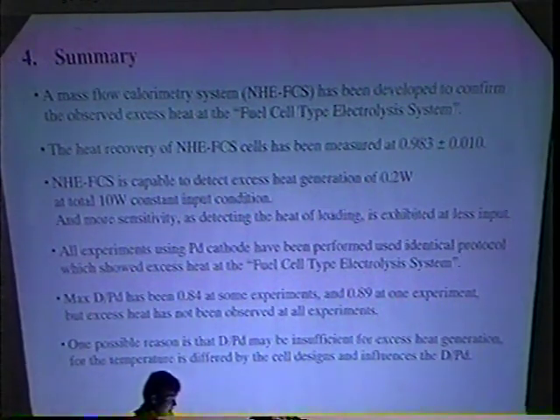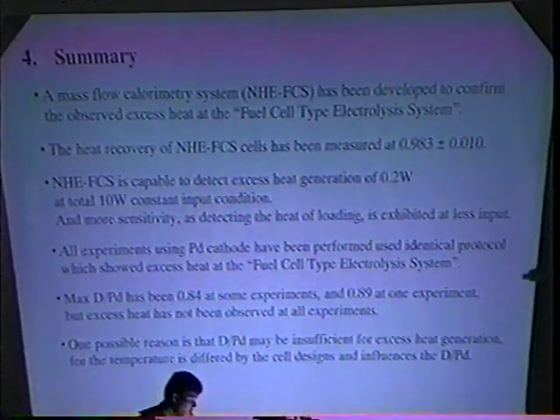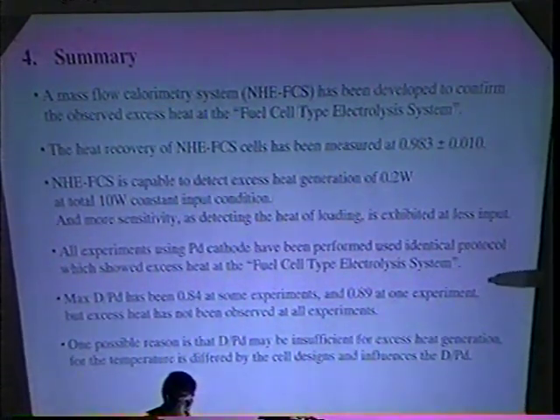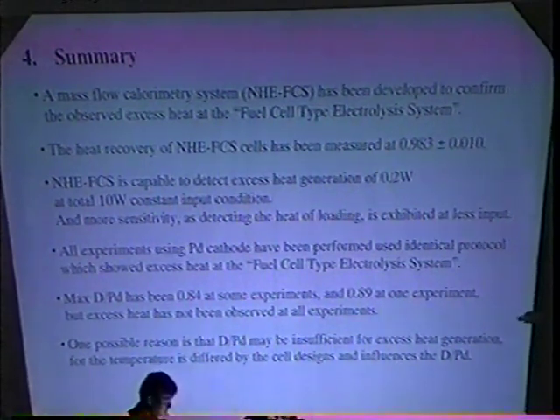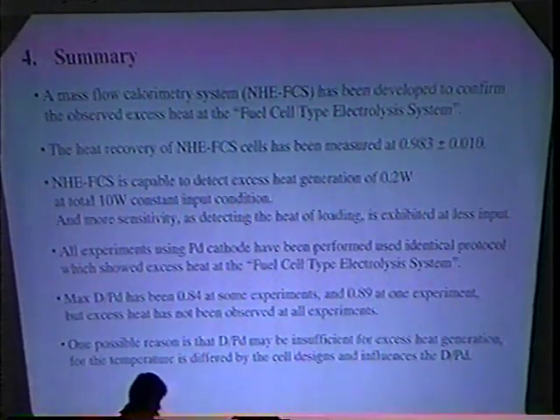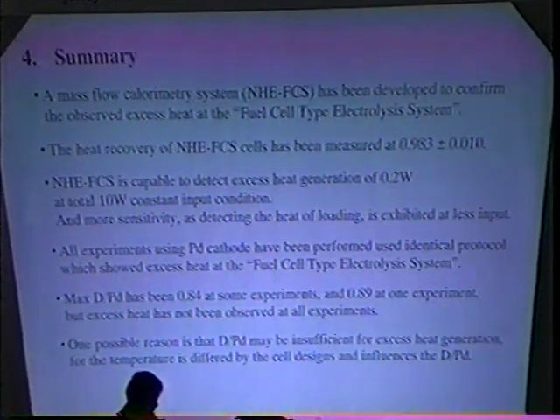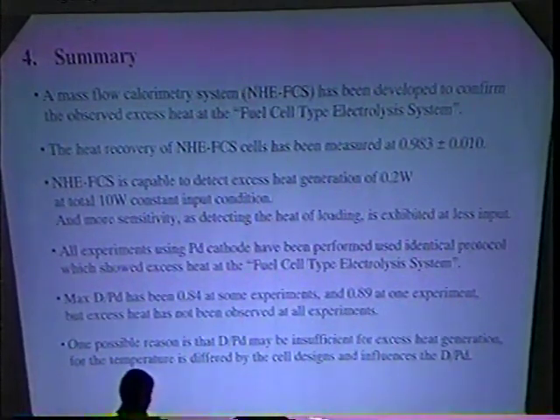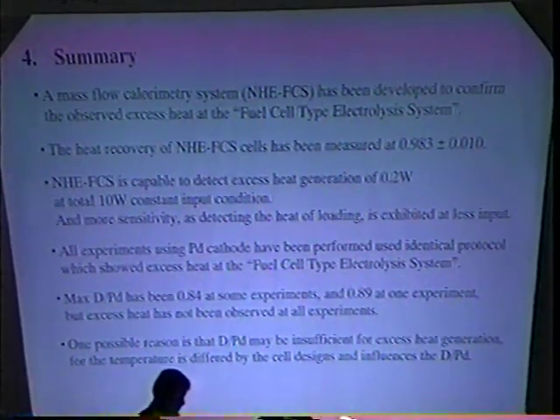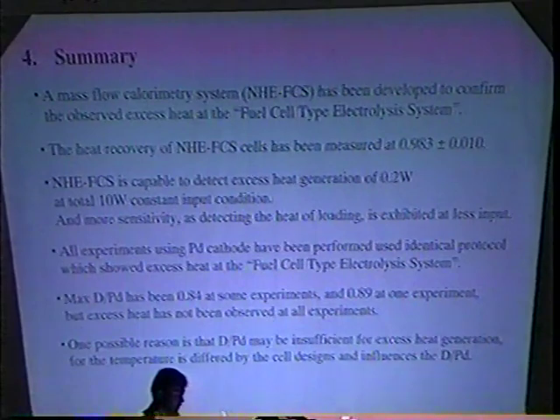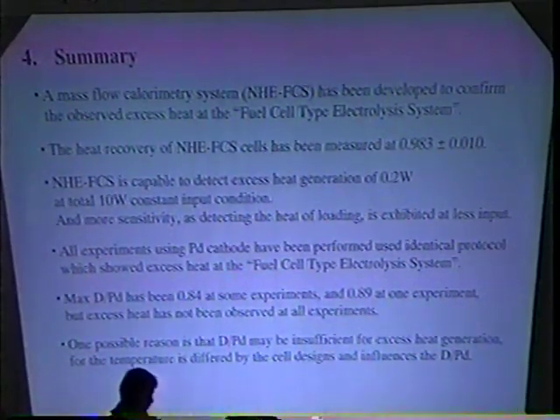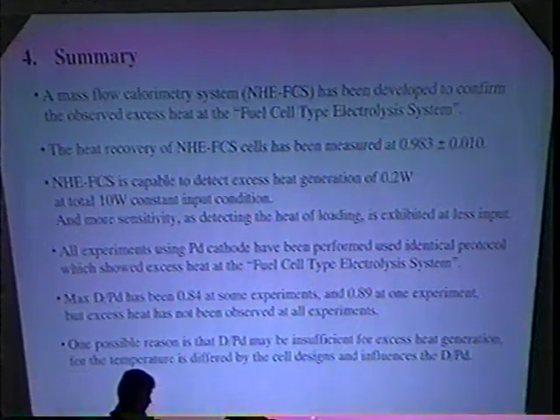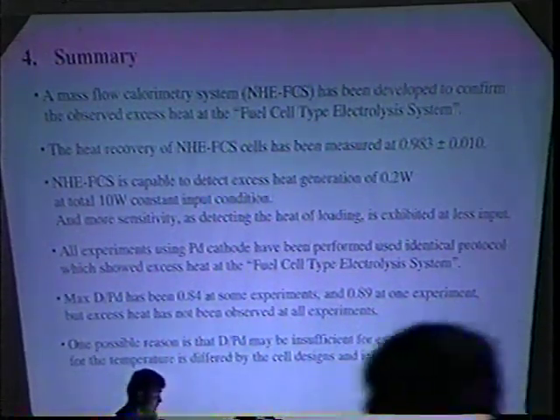All experiments using palladium cathode have been performed using an identical protocol, which showed excess heat in the fuel cell type electrolysis system. Max D by PD has been 0.84 in some cells and 0.89 in one experiment, but excess heat has not been observed in any experiment. One possible reason is that D by PD may be insufficient for excess heat generation, or that temperature differs by the cell design and influences the D by PD. Thank you.